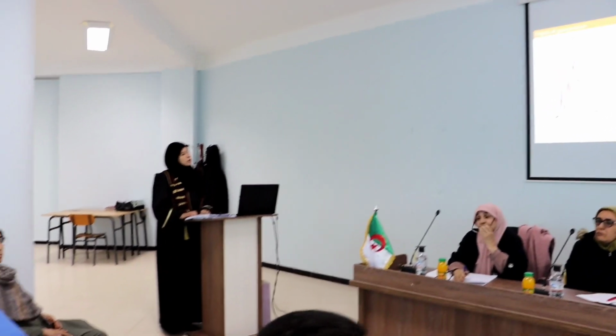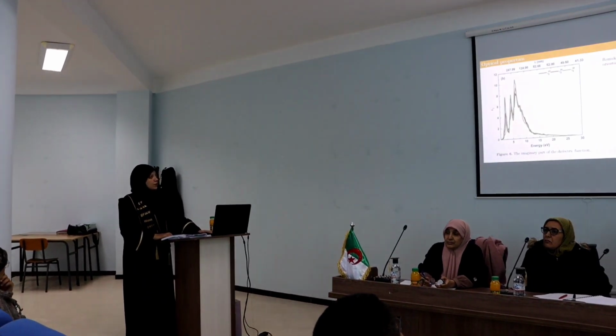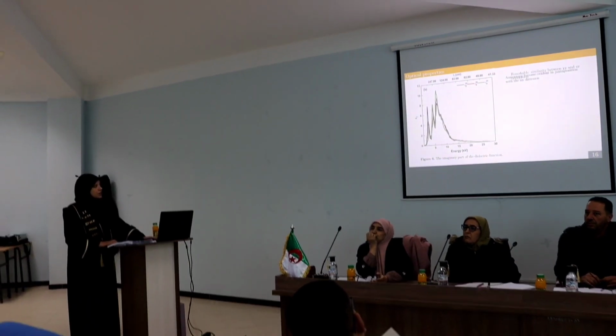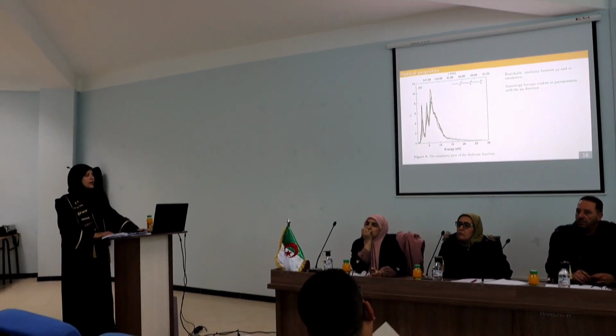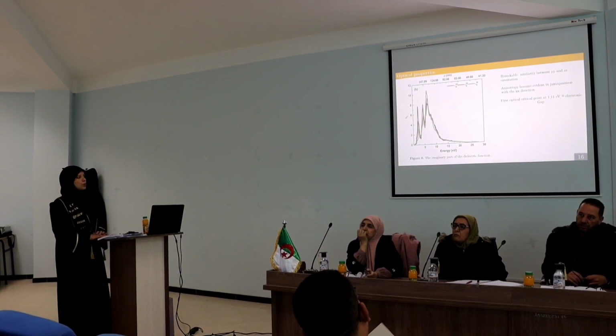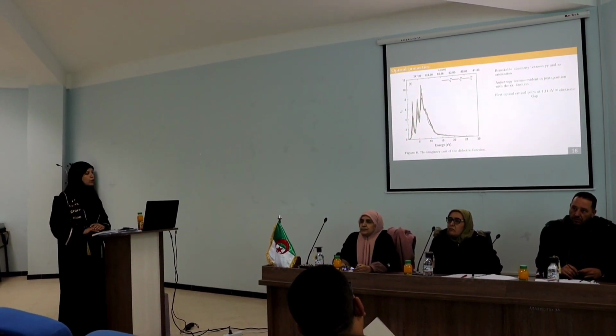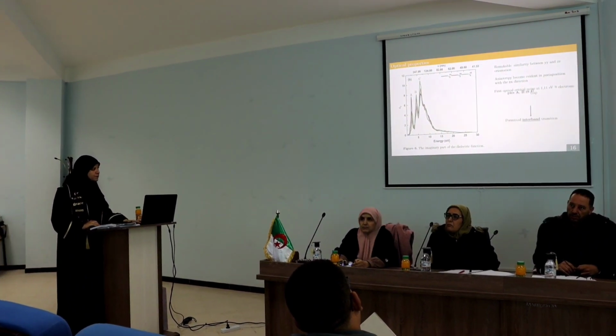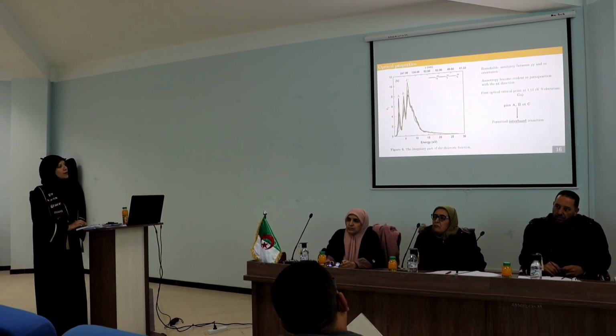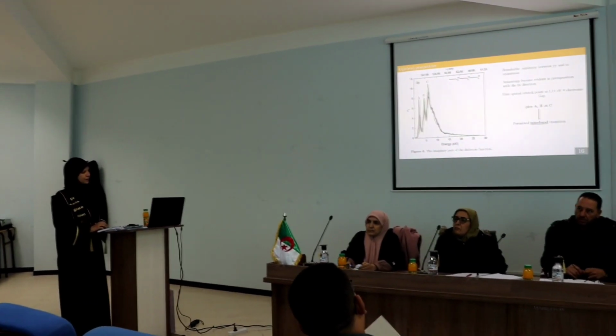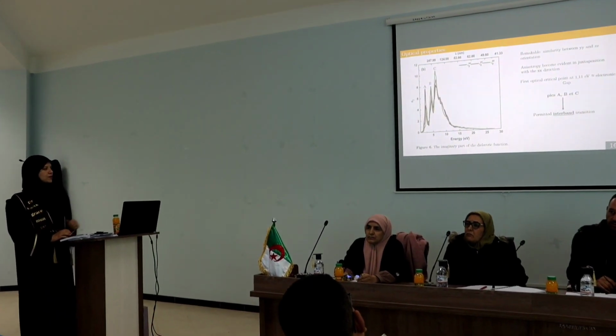In order to study how the material interacts with electromagnetic radiation, we study its dielectric function. The dielectric function has a real part and an imaginary part. This optical spectrum shows the imaginary part of our dielectric function. There is a remarkable similarity between YY and ZZ orientations, while an anisotropy becomes evident in juxtaposition with the XX direction. The first optical critical point at 1.11 electronvolt corresponds to the electronic band gap. There are three main peaks labeled A, B, and C. These peaks represent permitted interband transitions.